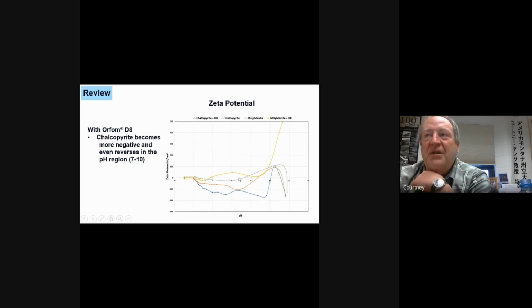In comparison, here's the moly without D8. That's this gray plot. Not a lot going on in there. It's hugging around 0. Pretty low numbers. Put Orfom D8 with the moly, you see a little bit of a change, but there's not a lot of change in there.